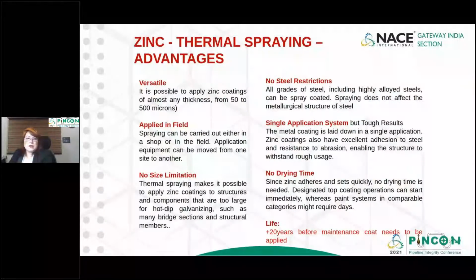Advantages of zinc thermal spray coating: it is possible to apply from 50 to 500 micron thickness. Spraying can be carried out either in a shop or in the field. It allows applying zinc coating to structures and components that are too large for hot dip galvanizing, such as many bridges, sections and structural members. It can be applied to all grades of steel, including highly alloyed steel, and the metal coating is laid down in a single application.